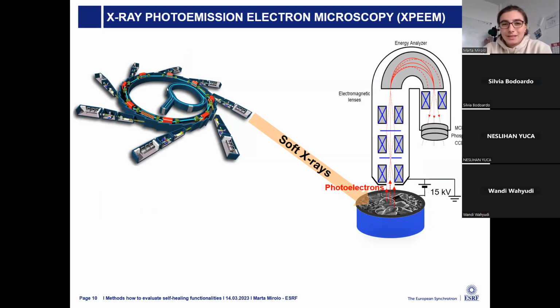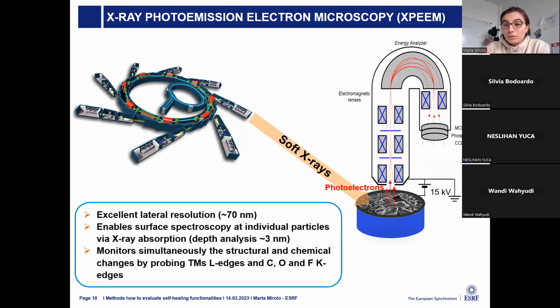One of these techniques, as I mentioned, is X-ray photoemission electron microscopy, in which we use the soft X-rays produced by a synchrotron to excite the electrons in our sample. The photoelectrons are then emitted by the sample, and they are focused in an electron microscope. And then what we obtain is images, like an SEM. So we obtain information with a good lateral resolution, with a good surface sensitivity. So we are really probing the very surface, roughly 3 nanometers. And we obtain chemical information as well, because we are probing the transition metal L edges, as well as carbon, oxygen, and fluorine K edges. So we can really study the SEI composition at the different particles in these composite electrodes.